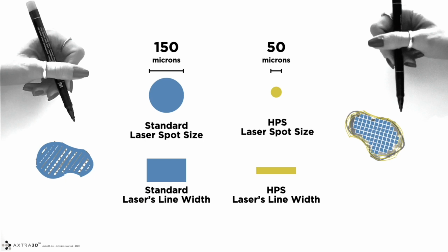In our case, the approach is completely different. That's the reason why today on Lumia X1 we are using a 50 microns laser spot size. Why? Because we are using the laser only to generate the contours. In general, 1, 2, 3, in the worst case 4 contours with the laser, because we are simply curing the cross-section using a DLP projector. So for us, the resolution of a projector doesn't mean the resolution of our system, because the resolution of our system is related to the spot size of our light engine. On Lumia X1, in this case, 50 microns.